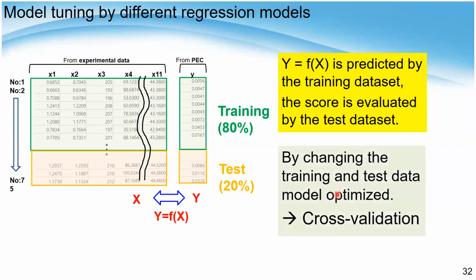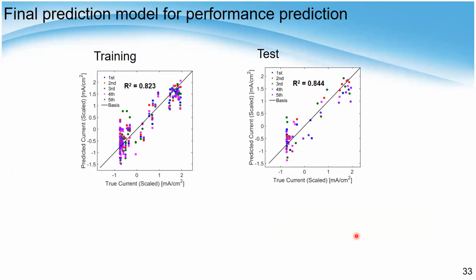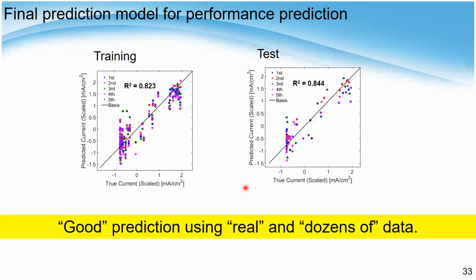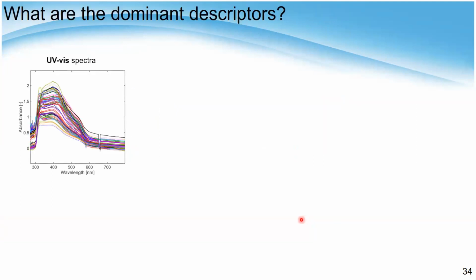So by changing the training and the test data combination, the model is optimized, which is called cross-validation. And this is a very typical method to do machine learning. And then by doing this, in the training and then test data set, you could see the R2 values were about 0.8, which were quite high. So it means that we could predict the performance nicely by using only dozens of data. So what are the dominant descriptors?